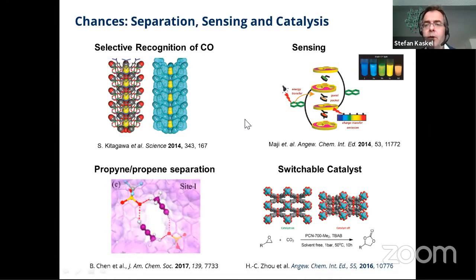So what is this good for? I don't know, but some people think it's very useful. For example, Kitagawa published in Science that some MOFs that show this switchability only switch their pores open for carbon monoxide, but not for nitrogen. Normally, carbon monoxide and nitrogen have very similar physical properties, like the critical temperature, and are difficult to separate with physisorption. But here, he developed a MOF that selectively opens the pore for carbon monoxide.